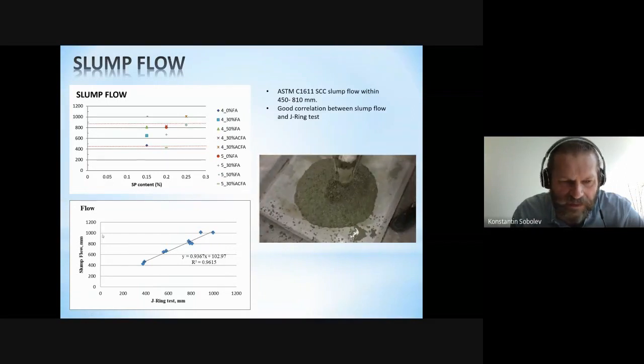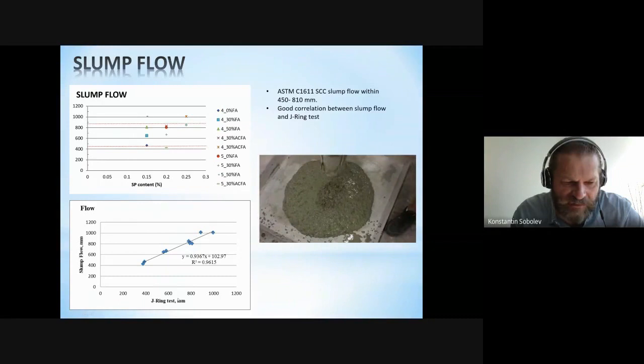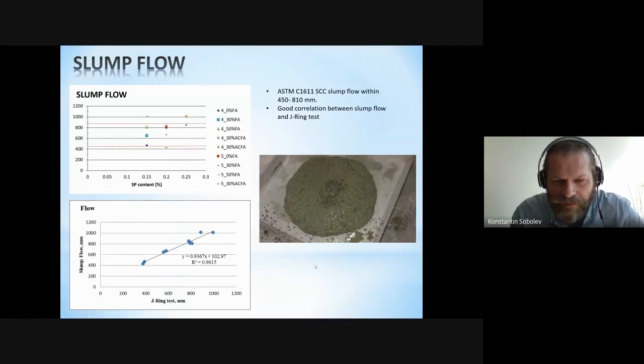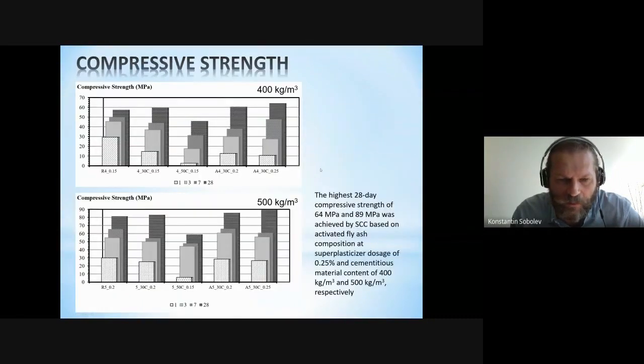We tested the self-consolidating concrete, and we tested also the J-ring test, and we found a perfect relationship there. Obviously, if we look at compressive strength development, and again in this experiment we just used class C fly ash, if we use 30% of fly ash as a replacement, or we have activated material, obviously the 3-day, 7-day, and 28-day strengths were really improved in these systems. So it shows the benefits.